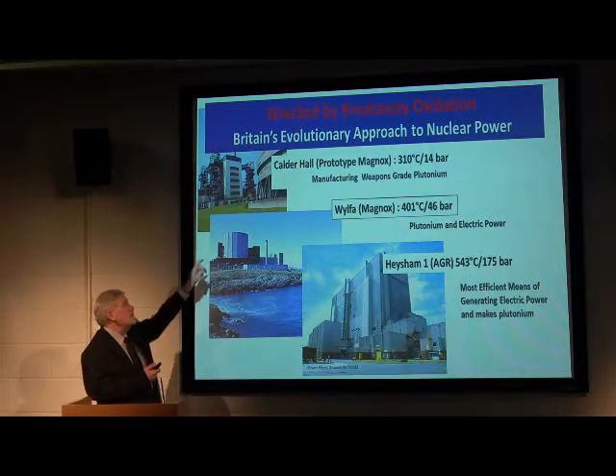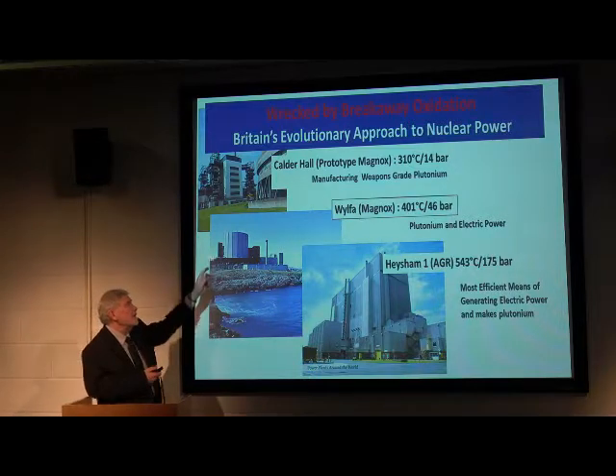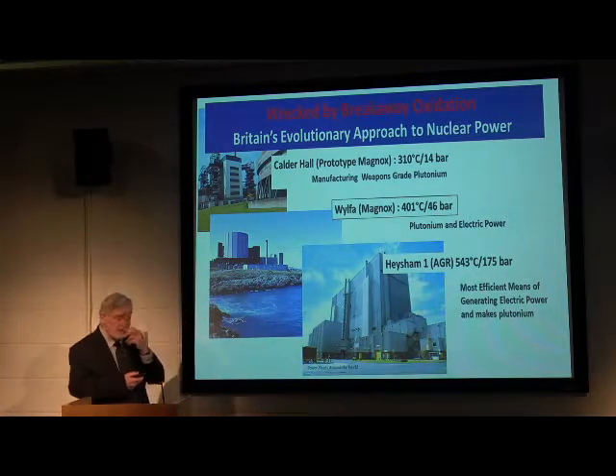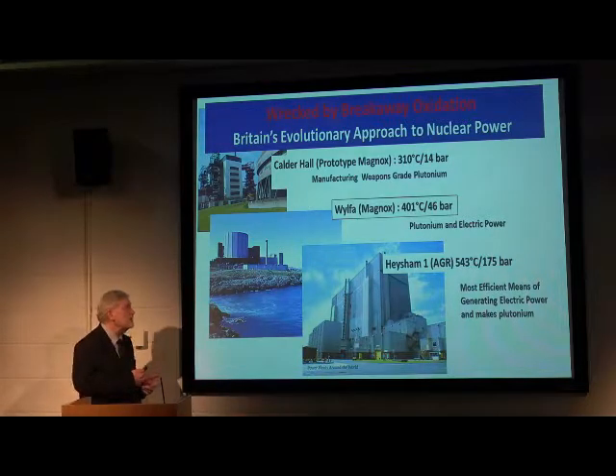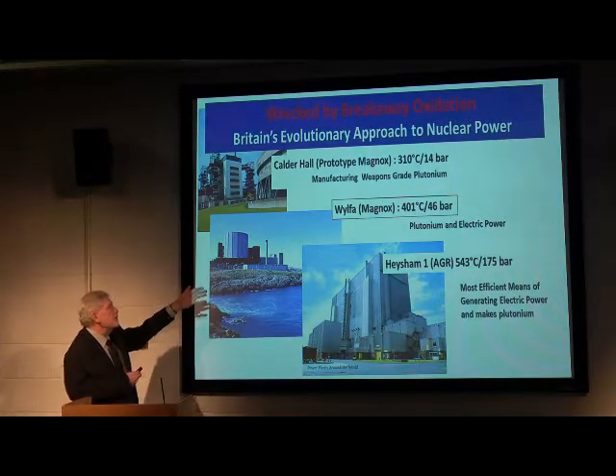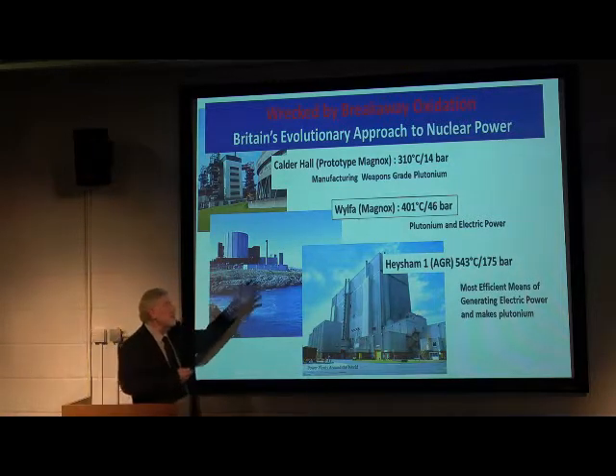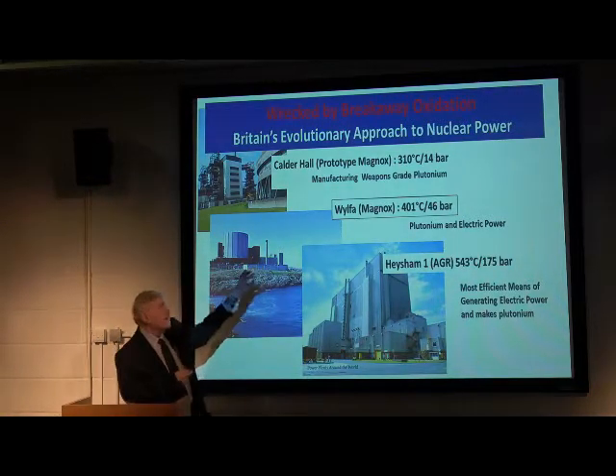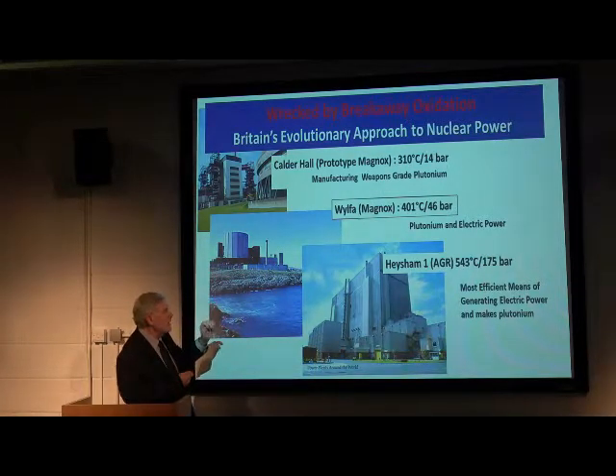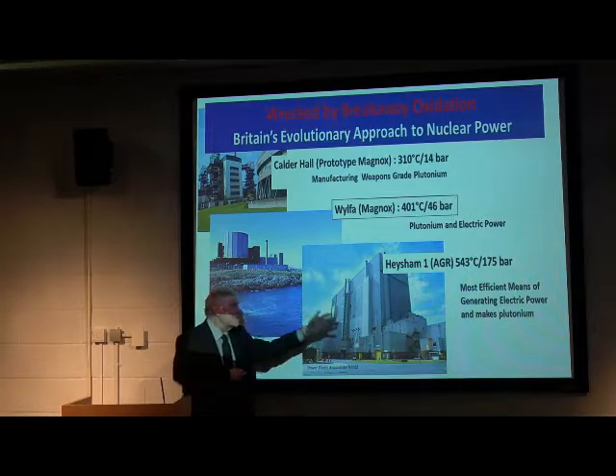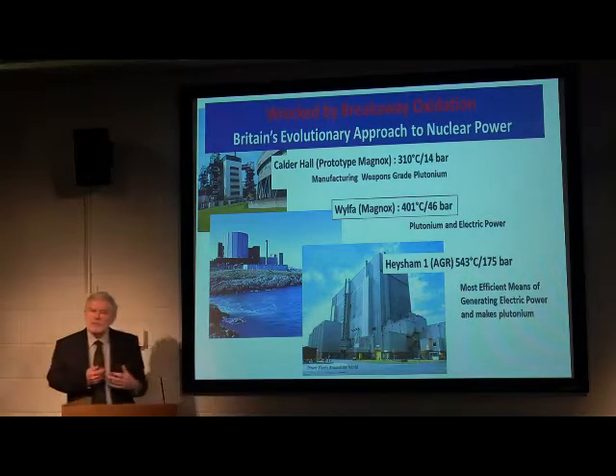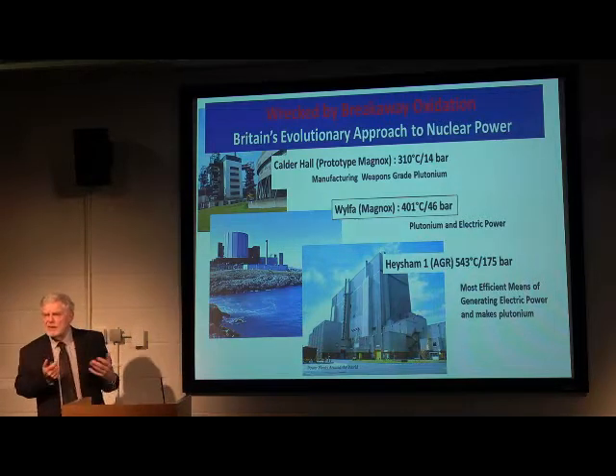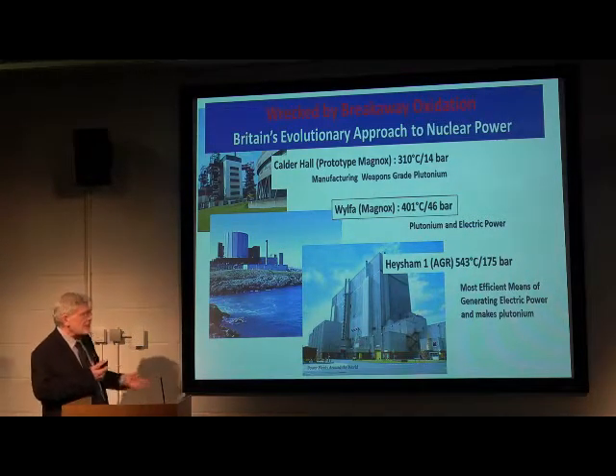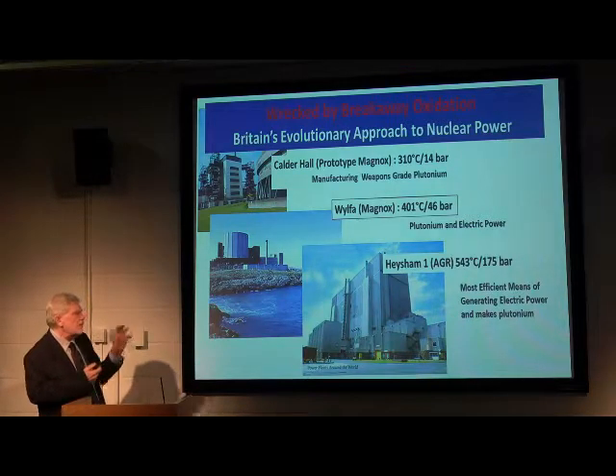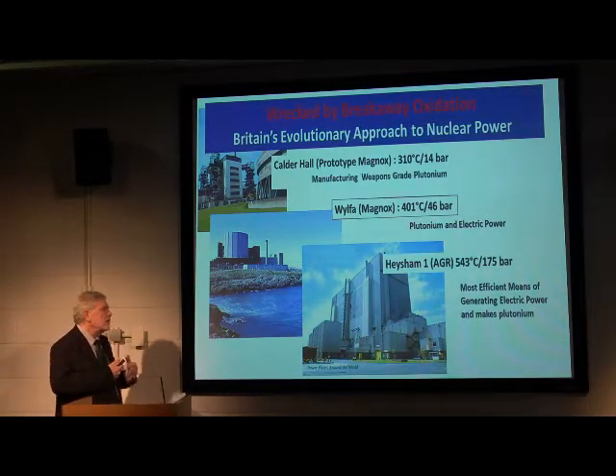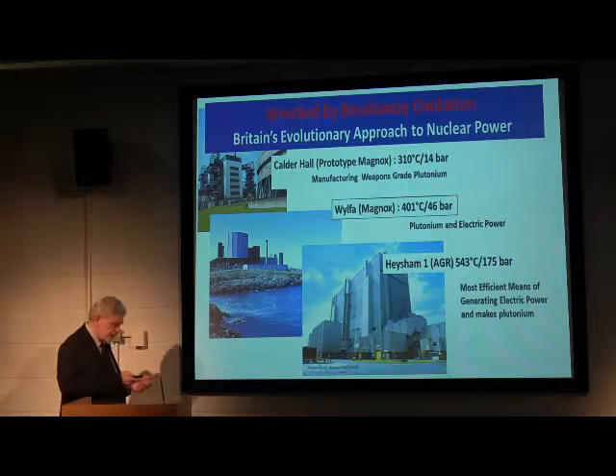But Calder Hall was the very first plant, running at 310 C steam temperature, 14 bar steam pressure. The next step was a more commercial design, Wylfa. That only shut down last year after about 40 years of operation. And we come to the advanced gas-cooled reactors. All of these were taking the heat away from the nuclear reactor and passing it through the system where it was used to boil water and superheat water to produce steam that went through steam turbines.